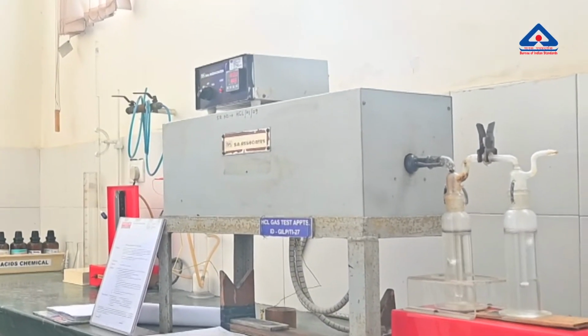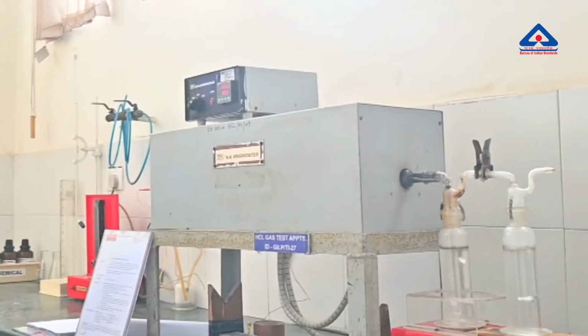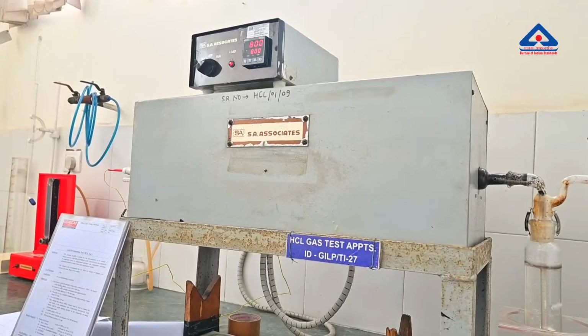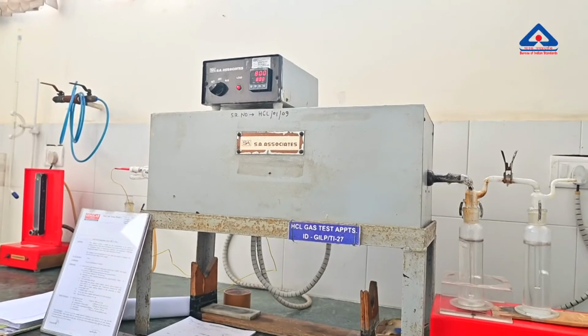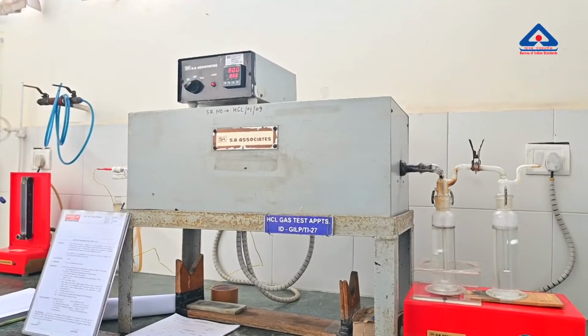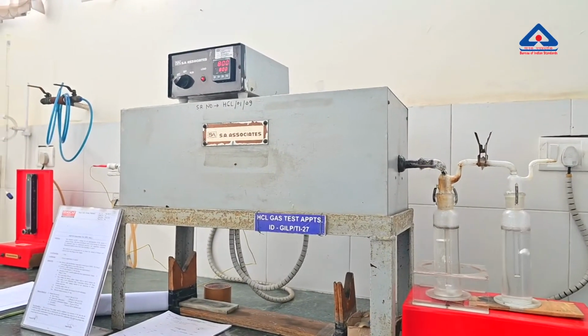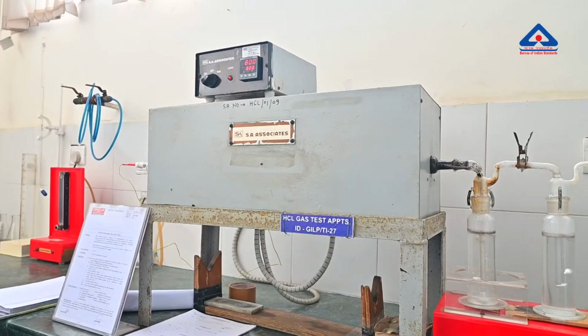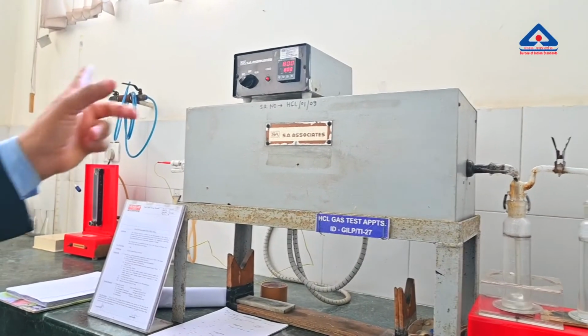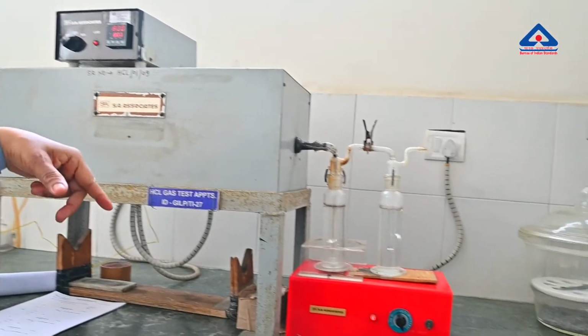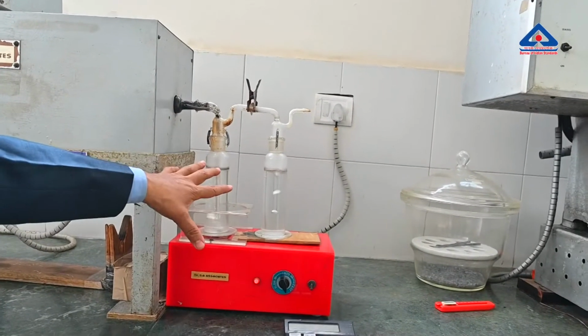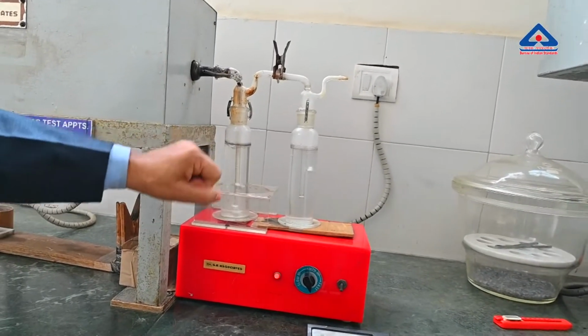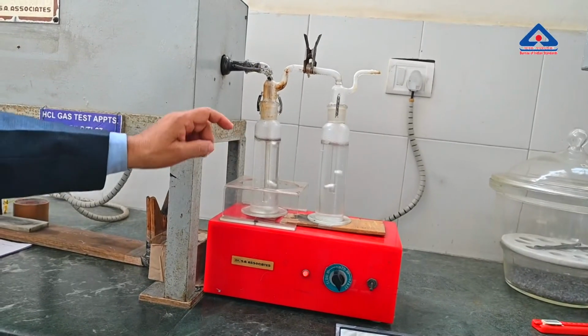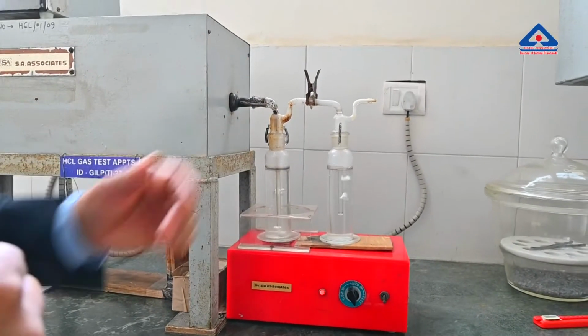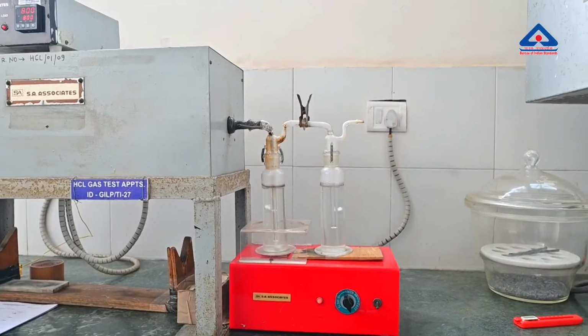The sample is kept at 800 degrees, and after burning, the limit for HCl content is maximum 20%. See here it is going on, and after completion of the period we take this sample, and the solution is titrated with chemicals as specified.